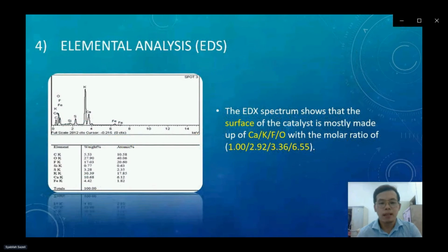Then is the elemental analysis. The EDX spectrum shows that the surface of the catalyst is mostly made up of Ca, K, F, and O with a molar ratio of 1, 2.92, 3.36, and 6.55.